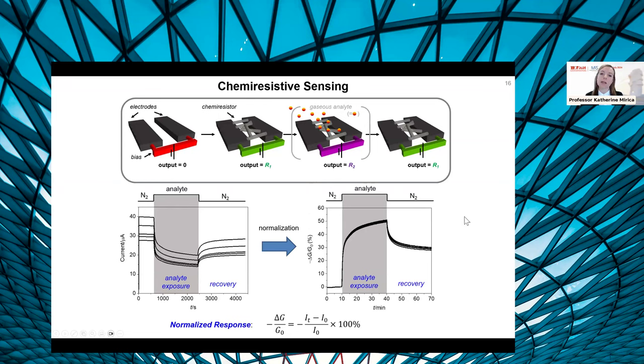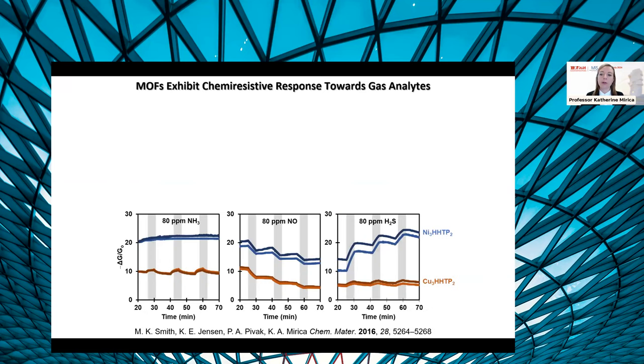So let's take a look at some real data for two different framework materials, both with the hexahydroxytriphenylene ligand, but interconnected with different metals, copper or nickel. So the metal is different, the ligand is the same. And we're exposing these materials in the chemiresistive device architecture to three different gases: ammonia, nitric oxide, and hydrogen sulfide. So I talked about the importance of gasotransmitters such as nitric oxide and hydrogen sulfide. Those are our main targets, but ammonia is also an important toxic gas and common biological interferent for these target gases as well. So that's why we're looking at that.